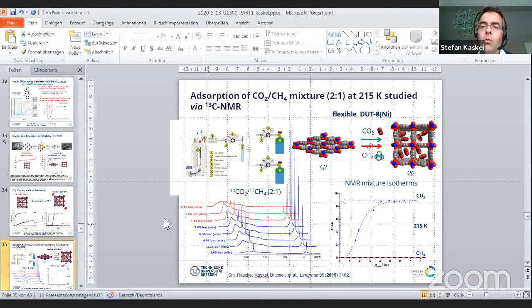Yes. So we measured the rigid variant also, and we detected the methane also in the rigid structure. Unfortunately, I don't have the slide here, but the signal of the adsorbed methane is a little bit aside from the isotropic signal, and therefore we know where we can detect it. And therefore we are quite convinced that it is at least below the limit of detectability by NMR methods.